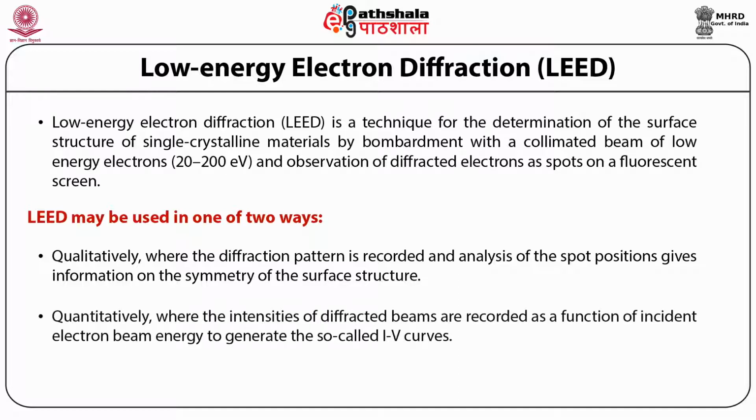Quantitatively, the intensities of diffracted beams are recorded as a function of incident electron beam energy to generate the so-called I-V curve, by comparison with theoretical curves. These may provide accurate information on atomic positions on the surface at hand.